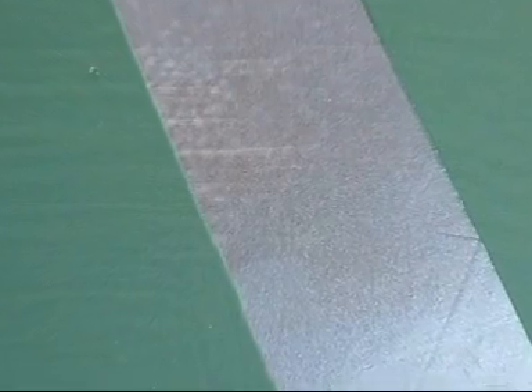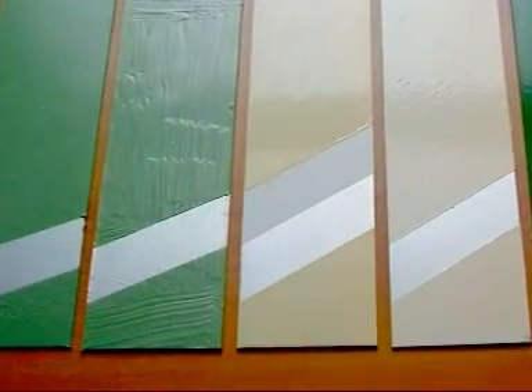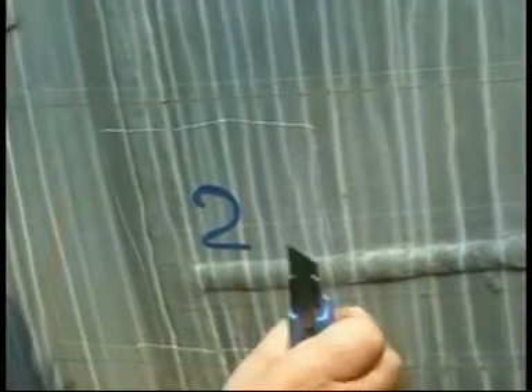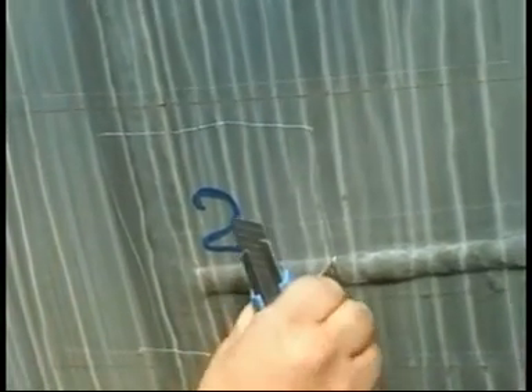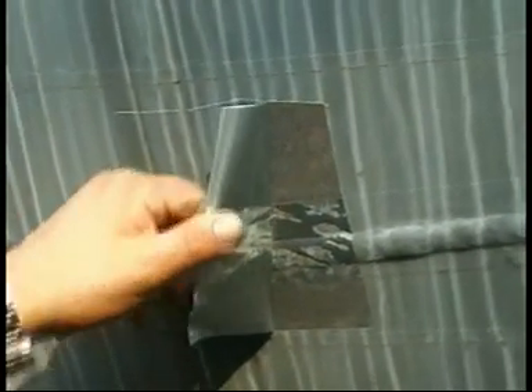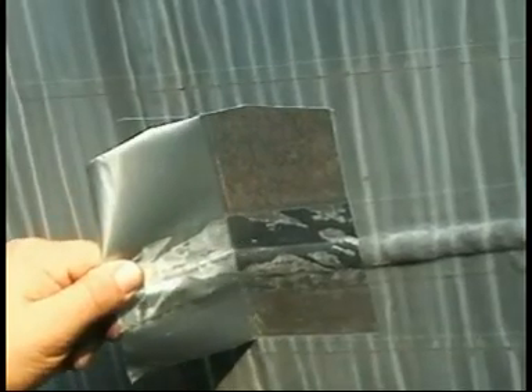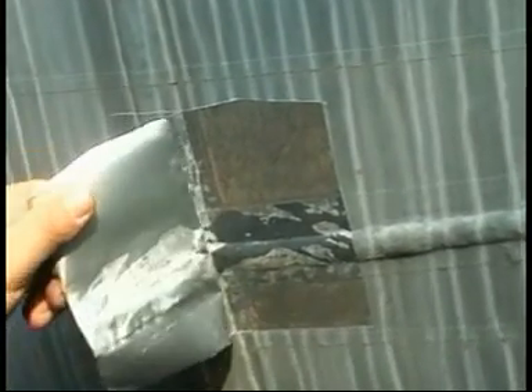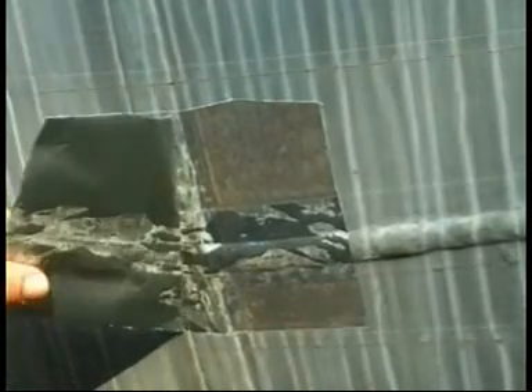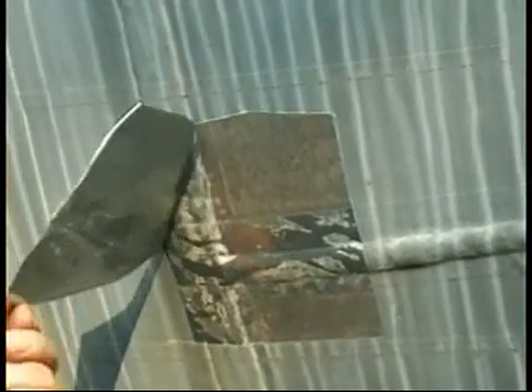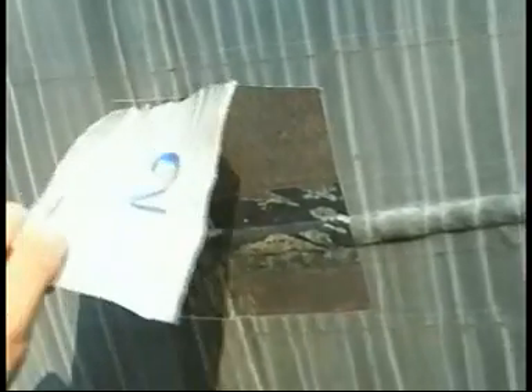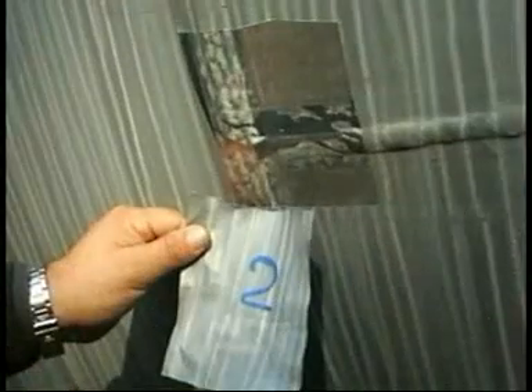It is also possible to paint the zinc tape in the same way as you would galvanized surfaces. This is a check of Isozin zinc tape on gas tanks after 20 years from original application. Samples of tape are removed and examined. As can be seen, the removal of Isozin zinc tape from the weld area shows the steel to be in perfect condition. There is also evidence that much of the electroconductive adhesive remains on the substrate surface. This is an indication that the bond between the zinc tape and steel is excellent. The sample zinc tape can then be taken away, the thickness measured with a micrometer, and the remaining life can then be determined.